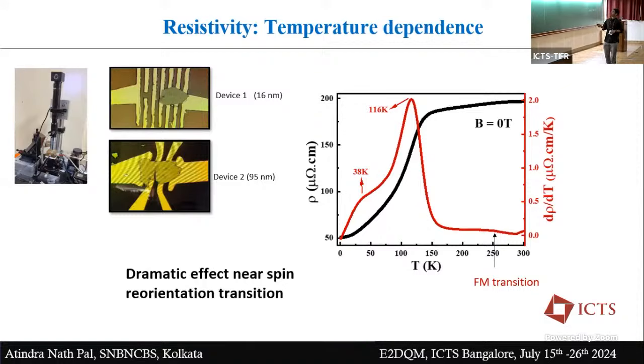The temperature dependence RT data, what you can see: we made two devices and did extensive transport on both. One is the thick layer limit, like 95 nanometer, and one is the thin layer limit, which is 16 nanometer. Both of them showed almost identical, similar transport features. Interestingly, if you see the rho versus T curve, this black line, initially the resistance shows metallic-like behavior, but near the ferromagnetic transition, which is somewhere here, 270 Kelvin, there is almost no feature.